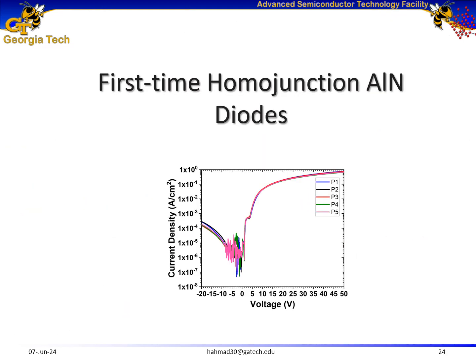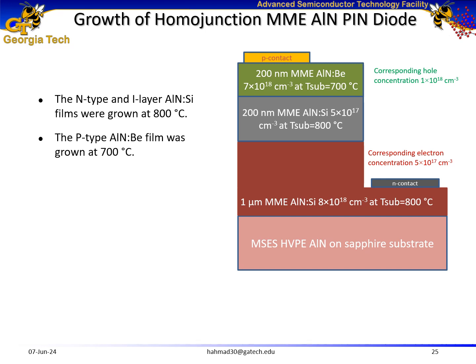So now the stage was set to perform the final study, which is first-time homojunction aluminum nitride diodes. This slide shows the layer structure diagram of these diodes, where I grew the N-type aluminum nitride and the I-type aluminum nitride, which are silicon doped at 800 degrees C substrate temperature, and I grew the P-type beryllium-doped aluminum nitride at a substrate temperature of 700 degrees C.